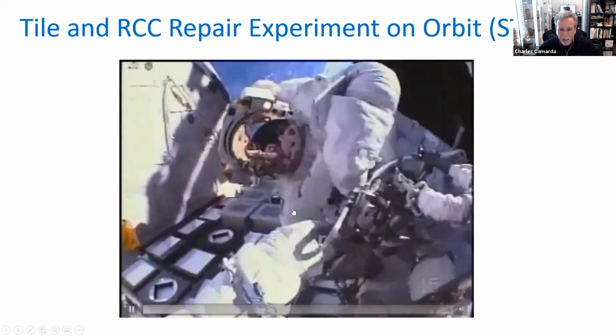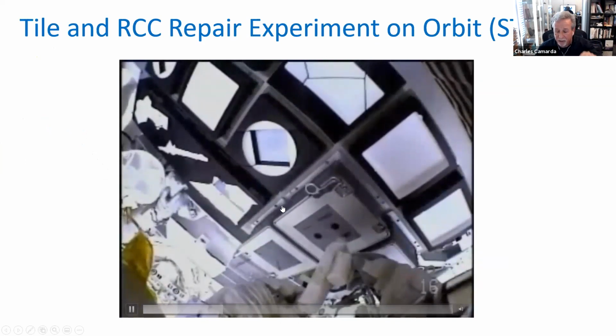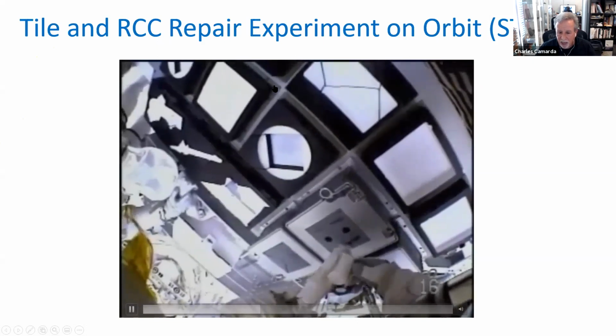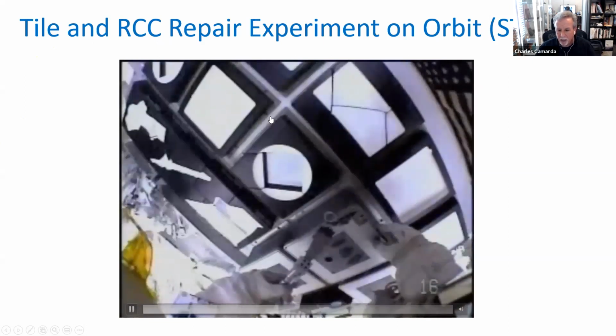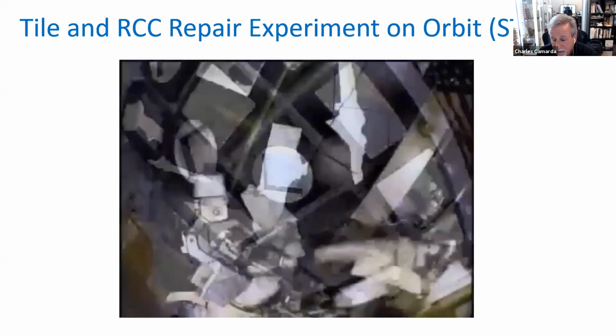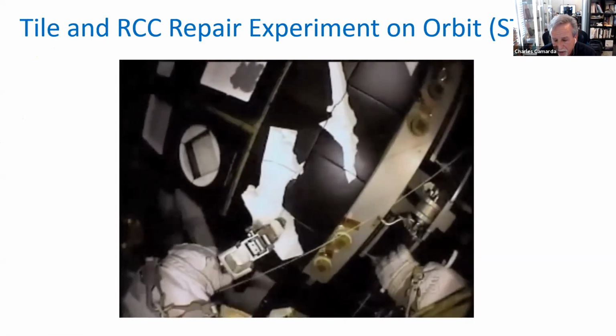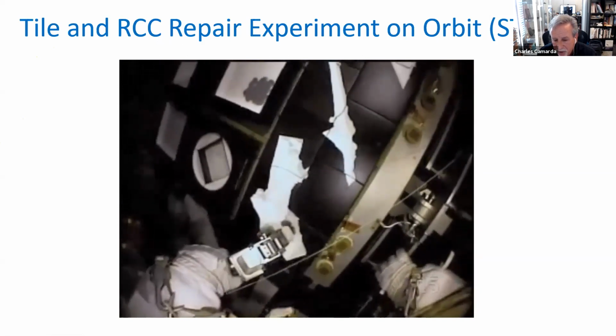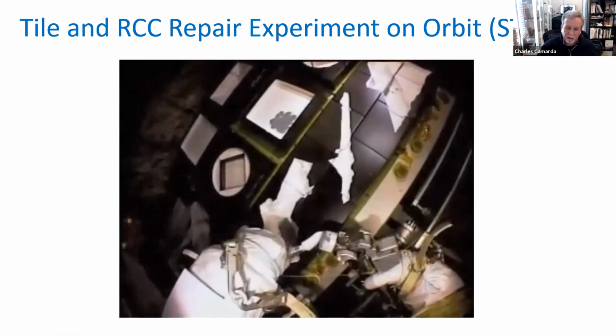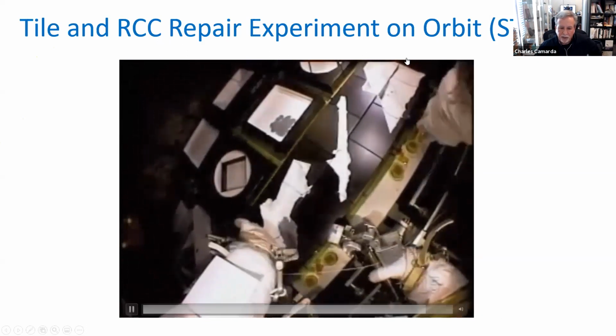The idea was, in our particular mission, this is Steve Robinson and Soichi Noguchi. We tested them on orbit, ways to fix the RCC material. We had damaged tile material in the payload bay. So this is where we're actually testing these ideas and testing the operability of these ideas in space. So here he's using a technique for basically coating the white surface of damaged tile so that it would have a high emissivity and wouldn't get too hot, but would radiate that energy to space. And it's showing you techniques for repairing it and applying it.